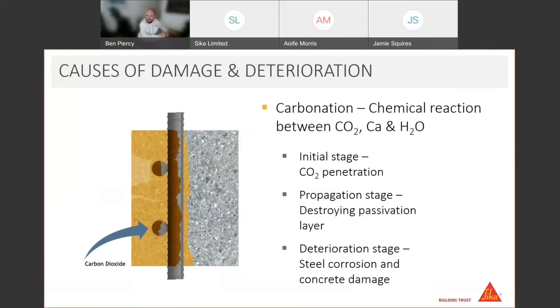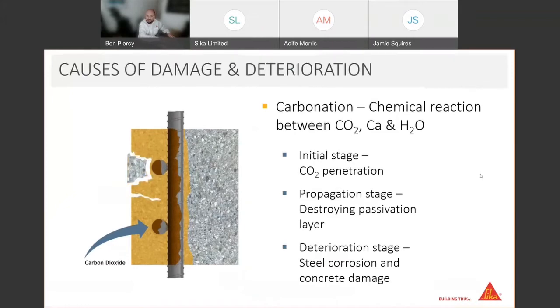You can see rust forming there on the rebar, and because rust is less dense than metal, it expands outwards. Now this is what puts that initial strain on the concrete itself and causes it to start cracking and spalling from this rust that's less dense that starts expanding. From that, naturally, we're into the deterioration stage, as you probably guess. This is where the concrete starts to crack and spall. All of this is defined under what can be called a carbonation front, which is essentially just the duration time it takes to start corroding.